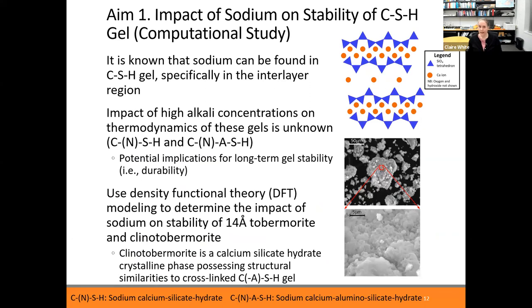So the first question we have is about this thermodynamics, and specifically, what is the impact of sodium on the stability of the CSH gel? Is it as thermodynamically stable as the conventional CSH gel? Because this can give us some indication of if the gel is going to change over time once the concrete has been poured in place. And we don't want the gel to change over time, because that can end up causing volume changes for the concrete. It can cause a loss of gel and therefore a loss of strength. It could cause the gel to be more prone to degrade when aggressive ions come in. So we really want to have an understanding of the stability of this gel.